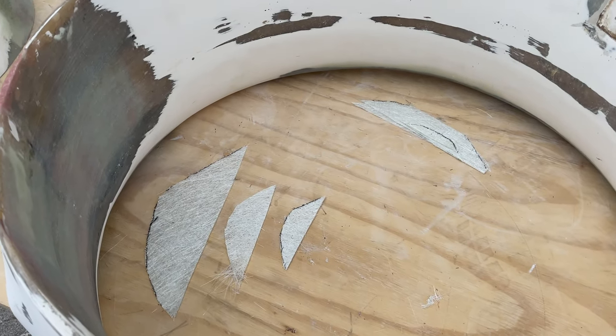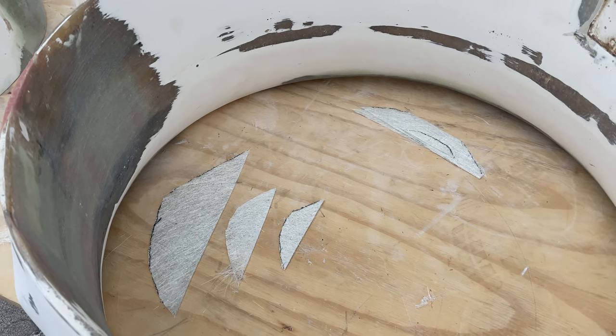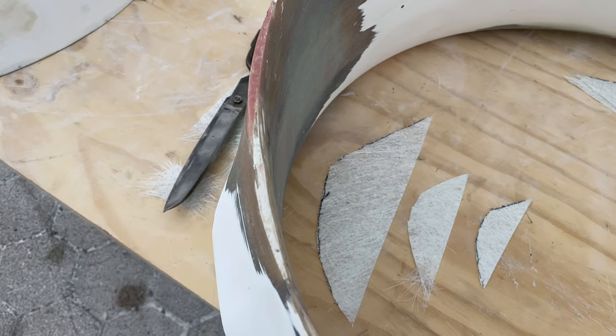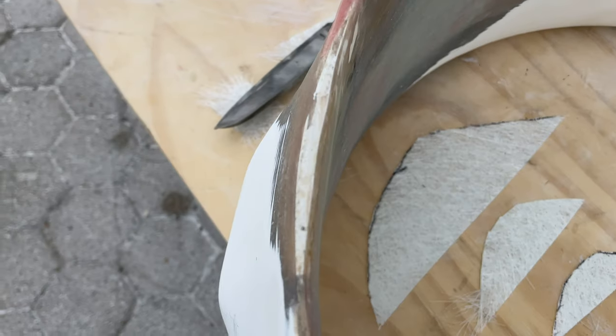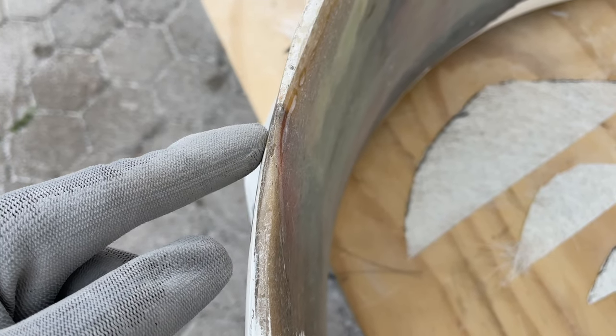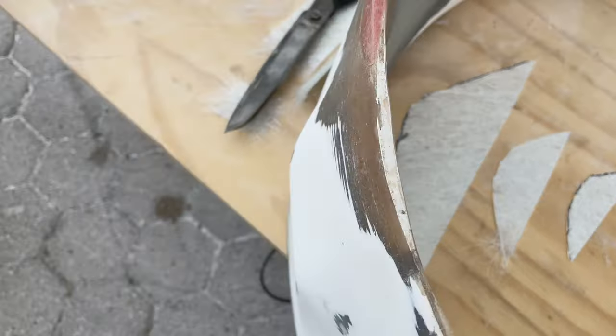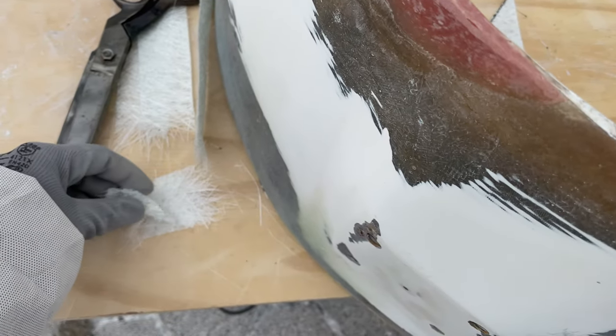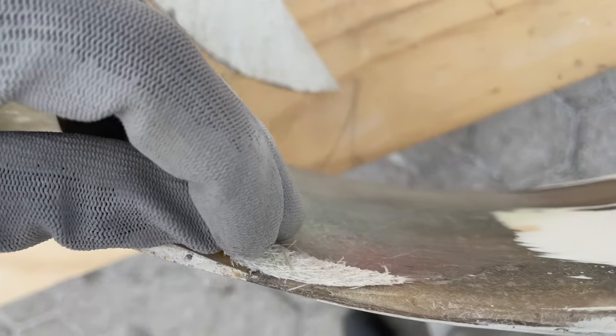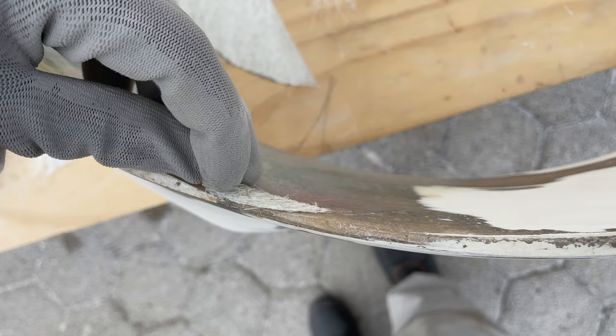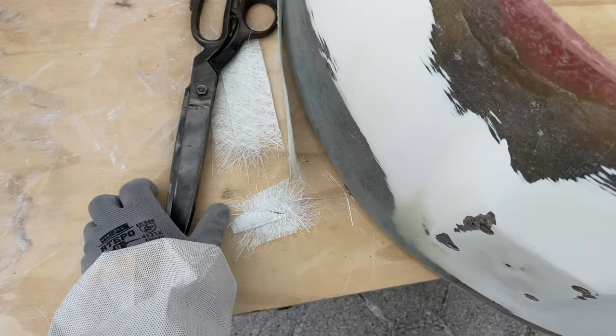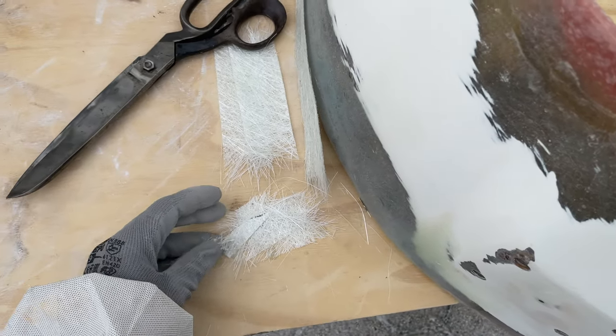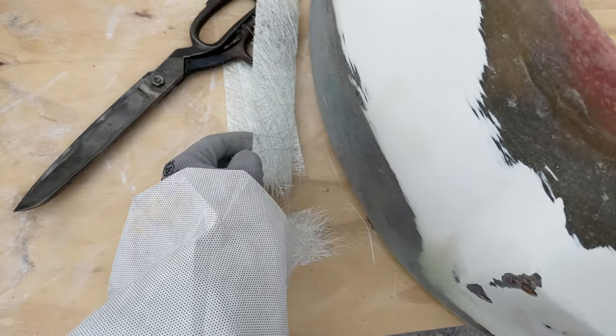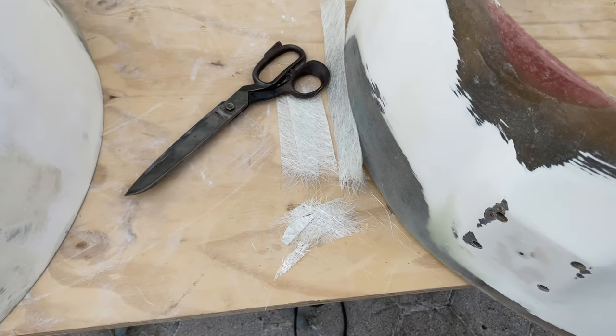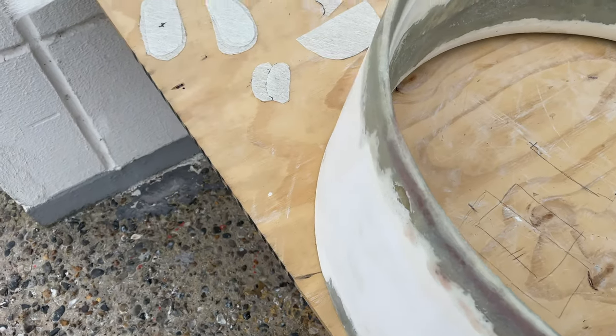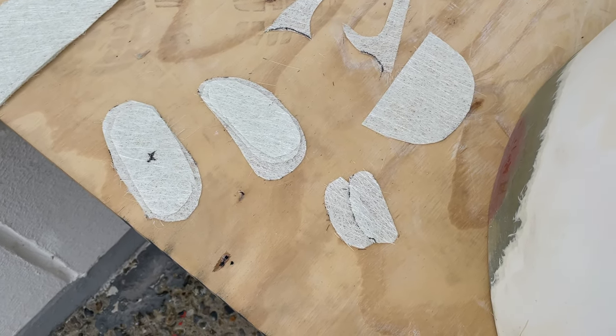Here we actually followed the steps that you see in all these YouTube videos about fiberglass works pretty exactly. So mark down the complete area on a fiberglass mat, cut it out, and then keep getting smaller in the new cutouts until you have this kind of ascending size of different pieces that when stacked on top of each other, will result in a piece of fiberglass that fills the hole completely. For the 450 gram per square meter mats, one thing that's very convenient is that each mat is adding about 1 millimeter of layer height. Therefore, it's pretty easy to calculate how many of the layers you need.